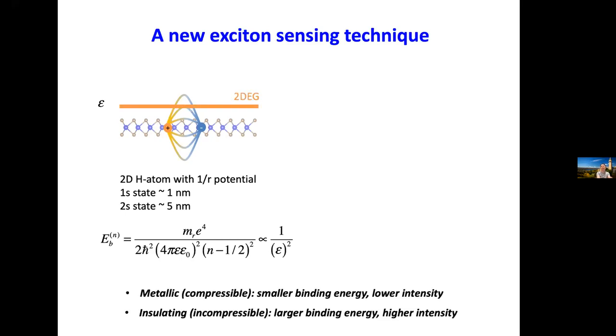Therefore, if you put something nearby, in this case a 2D electron gas, this will screen the electron-hole interaction and modify the exciton response. In particular, if the nearby layer is metallic, this will screen the exciton interaction more significantly, and we'll see smaller binding energies and smaller oscillating strengths, which just means lower absorption. If the nearby layer is an insulator, the screening effect is less, so the binding energy will be bigger and the intensity will also be higher.